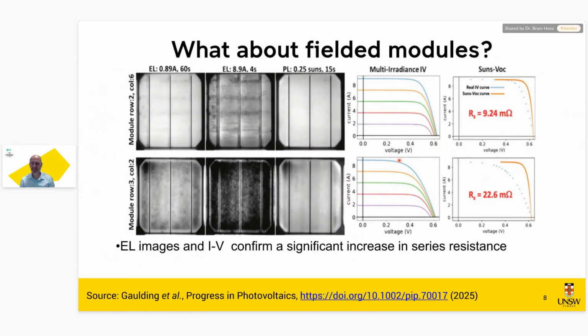these modules had 2 issues, and they were shown in 2 different ways in the solar cells. So the EL images and IV measurements confirmed a significant increase in series resistance. This is not typically something associated with UVID, but I will explain later why this is relevant. The PL images, so that's photoluminescence, where you're not extracting or injecting any current, show also a decrease, and that's the normal UVID that we see.